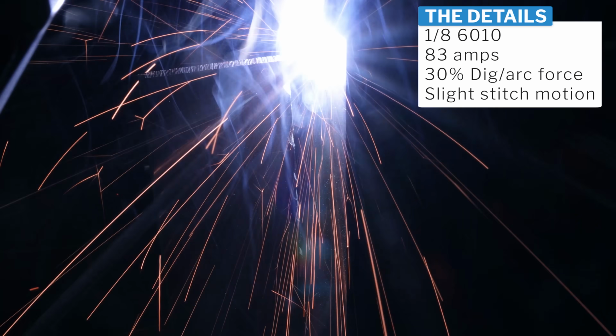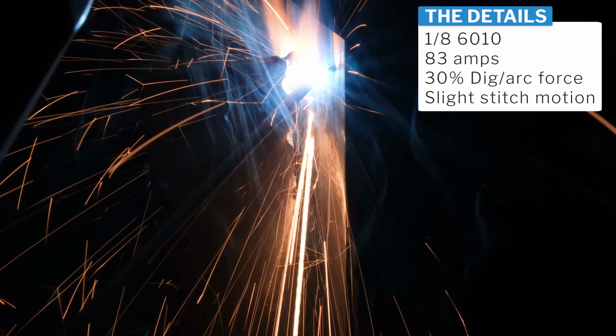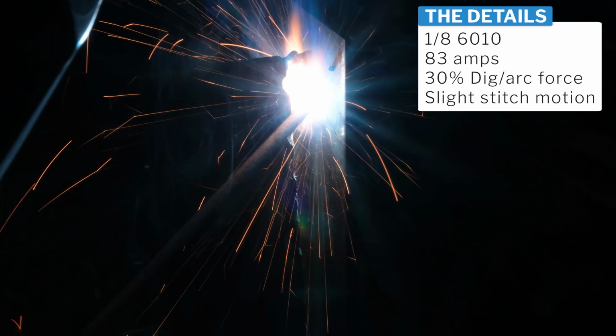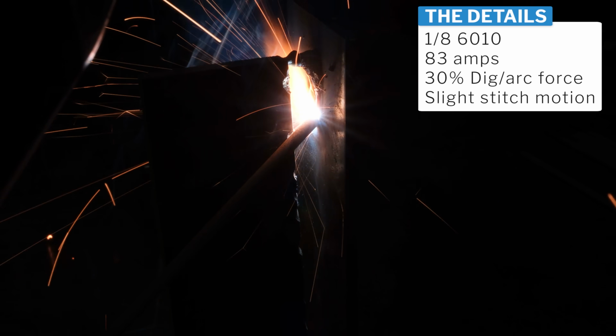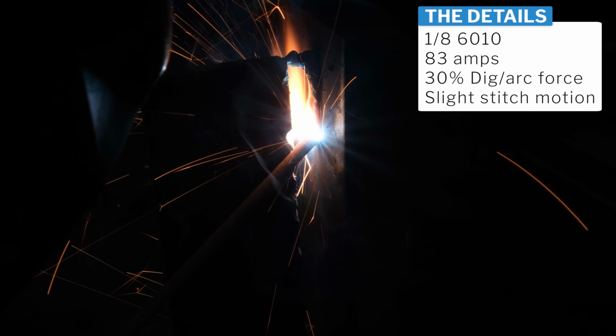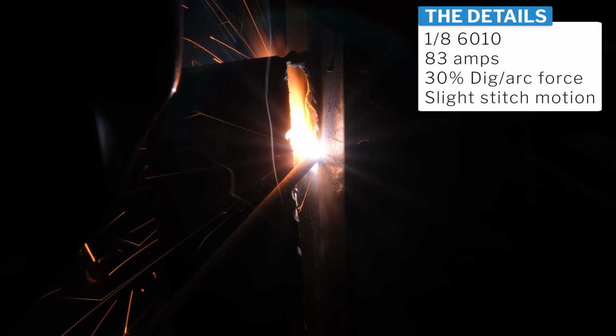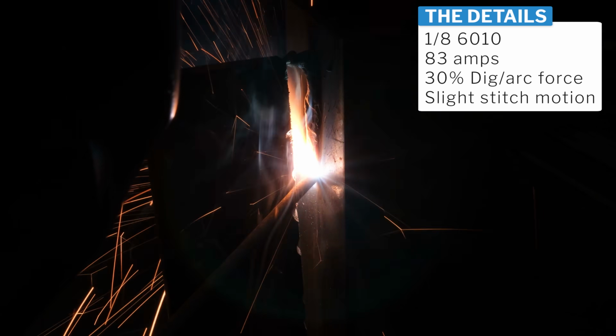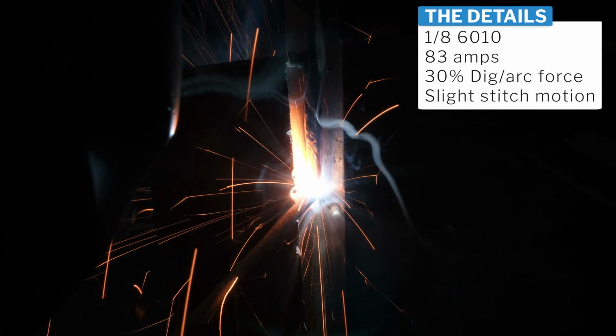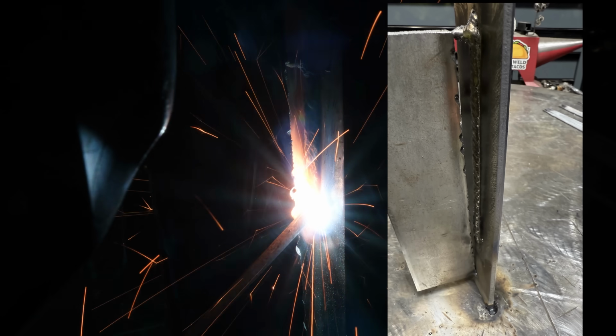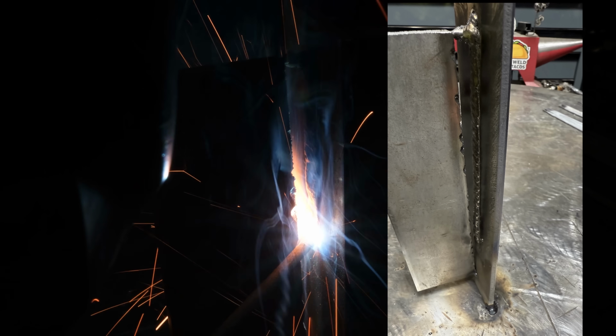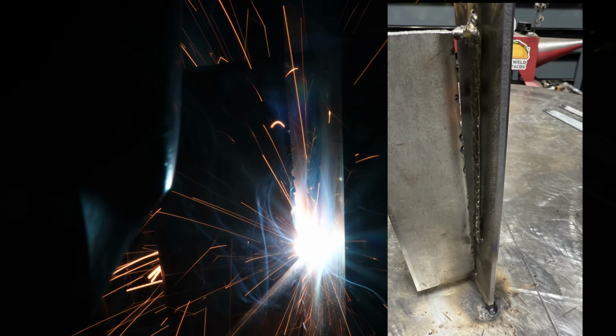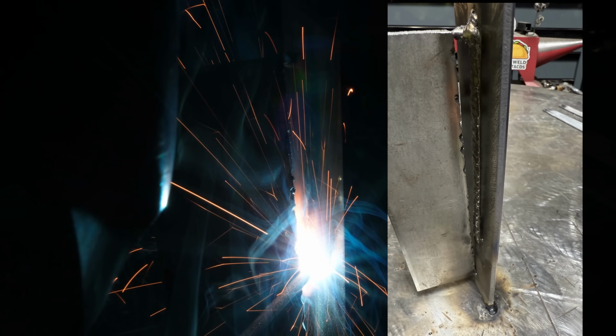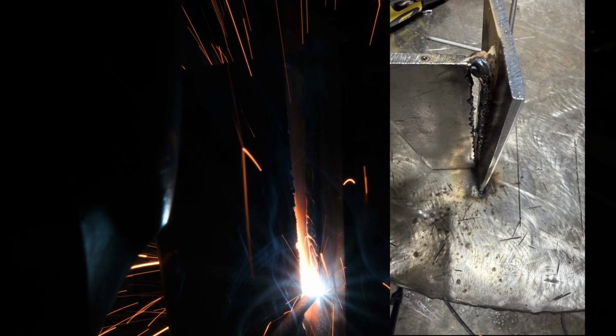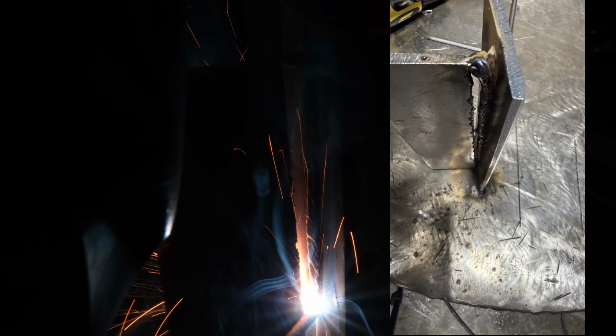So I'm going to strike the arc up top. Now, if you didn't have that joined together with a tack weld, you'd have to stack metal to try and get it tacked together like I did. The technique I'm using is like a slight drag angle, and I'm doing a little bit of a stitch motion. The main reason I'm stitching it is to keep the flux on the rod burning off consistent. If I just try to do a single pull, one motion stringer, what would end up happening is you tend to get arc blow because the flux won't burn off consistently.